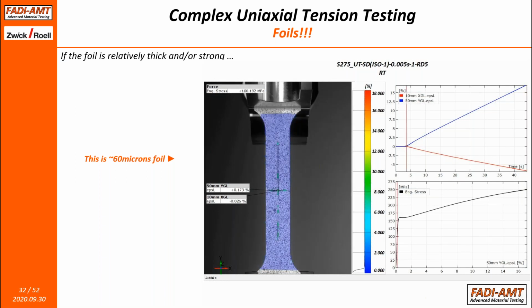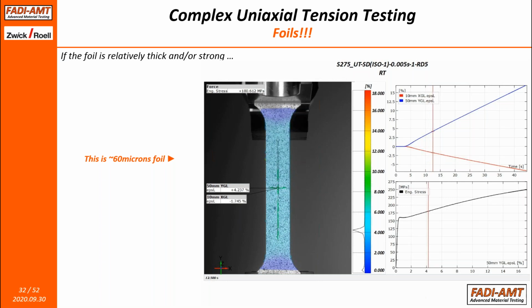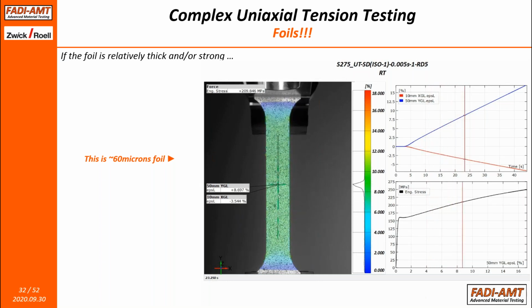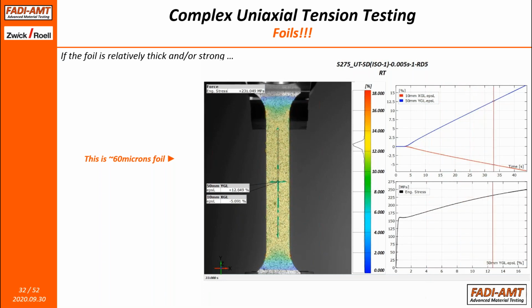And again, I want to show this video again. That's what we typically look for. Regardless of the strength and thickness of the material, we look for nice deformation without any significant hot spots, and ideally we would want to see failure in the middle of the sample.